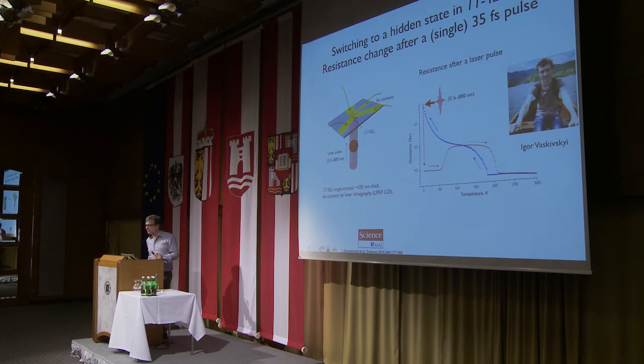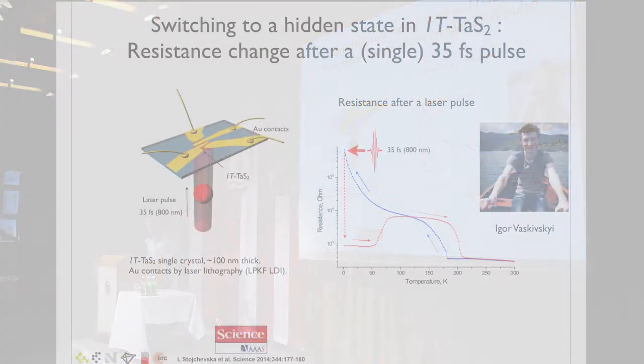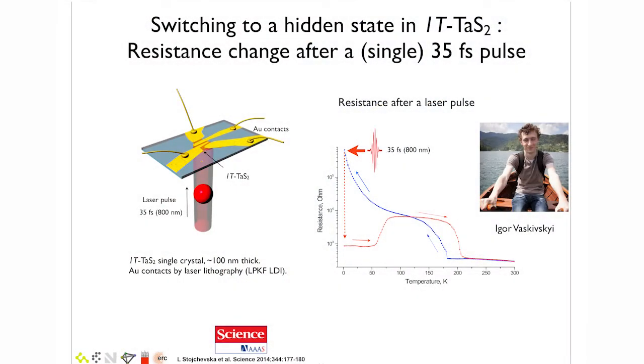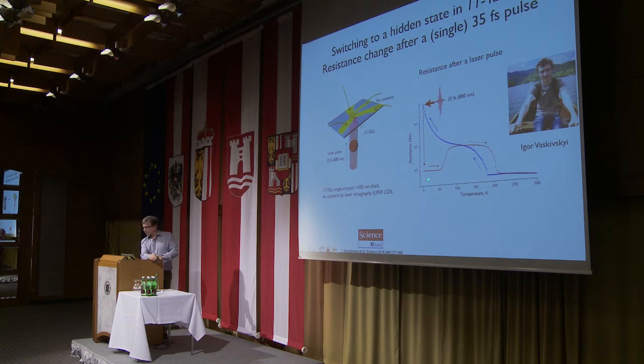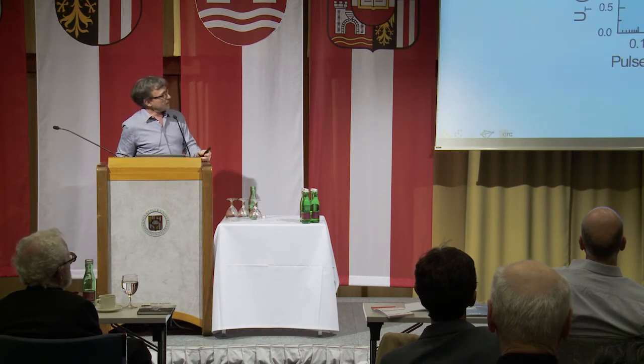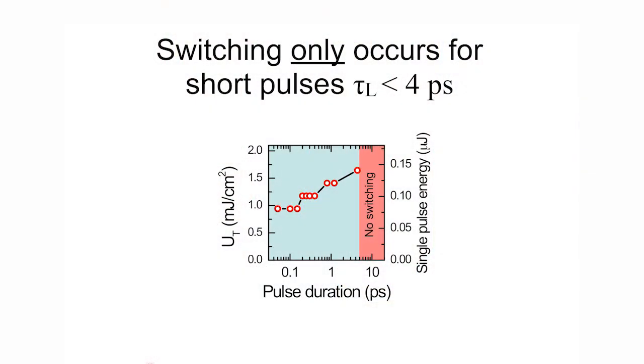So Heeger did the obvious thing, put contacts on it. It took a while to do it right, but eventually we found that, indeed, after a single 35 femtosecond pulse, the resistivity changes by 3 orders of magnitude. Unfortunately, it doesn't go to 0, a bit of a disappointment, but nevertheless, here we are. And as you heat it up again, it recovers and eventually joins up with the usual state above at high temperatures. Now, what's particularly interesting is that all this can only be done with very short laser pulses. You can't do it with long pulses, and that's related to the mechanism, but I don't have time today to go into detail.